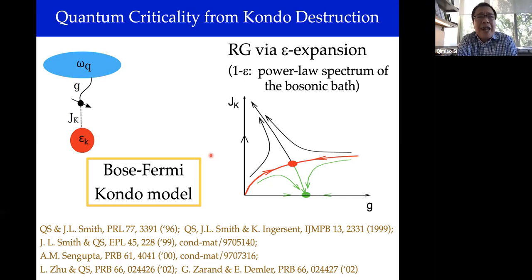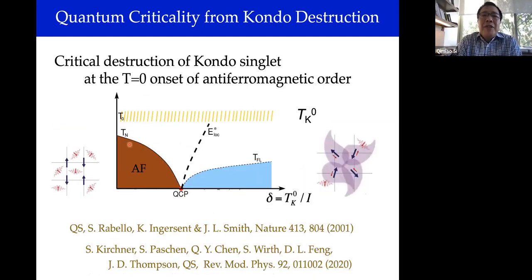But so far, what has been done was sort of Hall effect, which I will not actually show a plot, but there's a characteristic crossover. Let me just mention it. If you do an isothermal scan of the Hall effect, and if you can be sure that the Hall effect is primarily the normal contributions associated with the quasi-particles, then at finite temperature there's a rapid crossover. And the middle of the crossover is the E star scale.